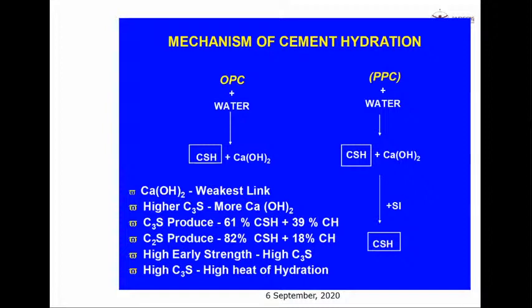But what happens if you use a higher water cement ratio? This calcium hydroxide gets washed away or carried away out of the concrete matrix while you cure the concrete, and that is why probably you would have noticed some white efflorescence or some white substance coming out of concrete when you start curing it. This is nothing but the calcium hydroxide, which is washed away due to the excess water cement ratio you have used during the preparation of the concrete itself.